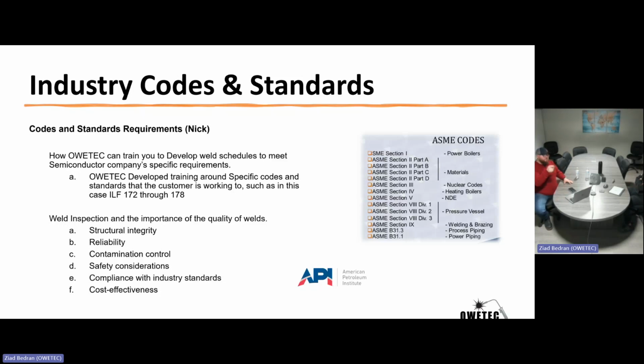If my coupon out is bad, the inspector is going to start going to look. If the weld he looks at fails visual, they borescope. Fails borescope, they cut it out. And they start cutting until they find 2 in a row that are good. It can be more critical or less critical depending on who you're working for. That's normally what happens. In the semiconductor, a lot of tubes are so small that even a borescope can't really fit in there, right? So yes, it would be hard to verify.